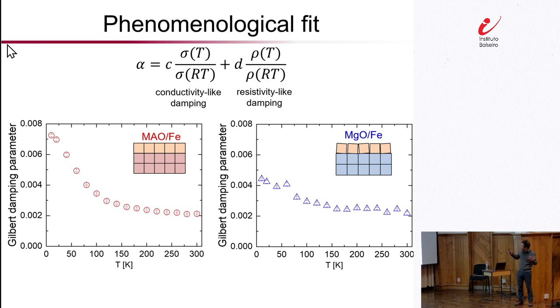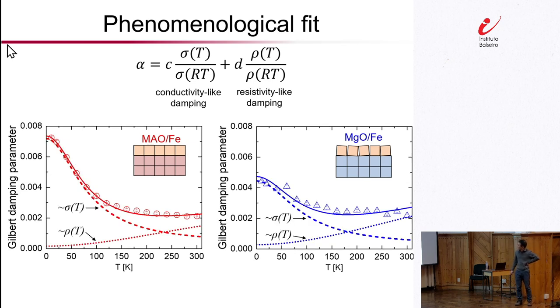Now, the easiest thing that we could do, without knowing any theory, is just try out this phenomenological model, right? So separating the damping into these two parts, one related to the temperature dependence of conductivity, the other related to the temperature dependence of resistivity, and simply adding them together with these two adjustable parameters, C and D. And to our surprise, this simple model works surprisingly well. It captures essentially the temperature dependence of the total measured Gilbert damping. So this seems to be a good indication. It's quite promising in that it appears to empirically confirm the idea that damping consists of both conductivity-like and resistivity-like contributions.